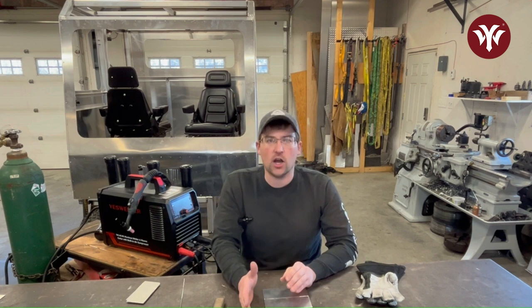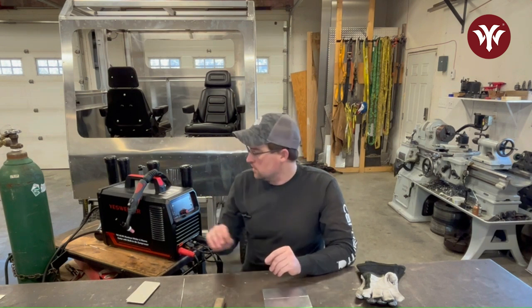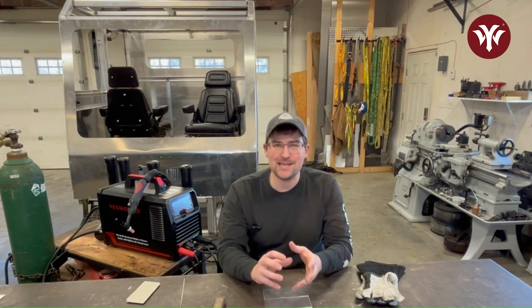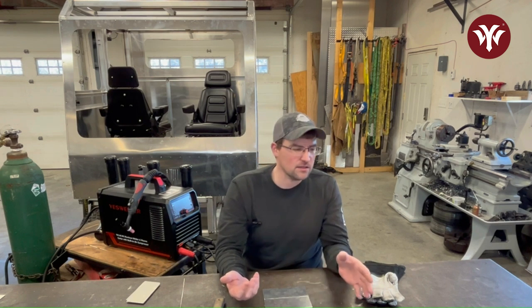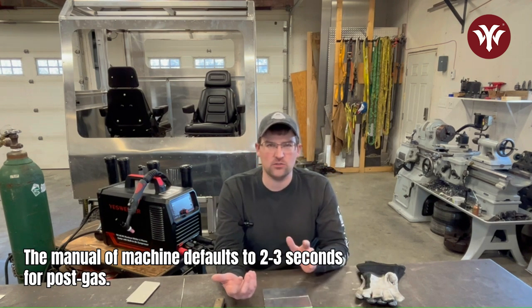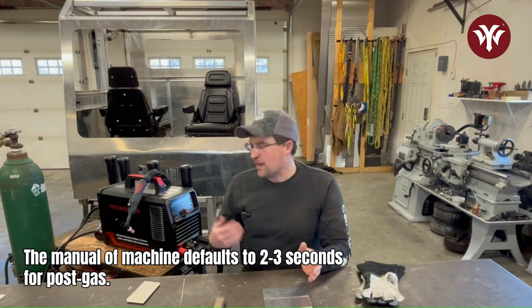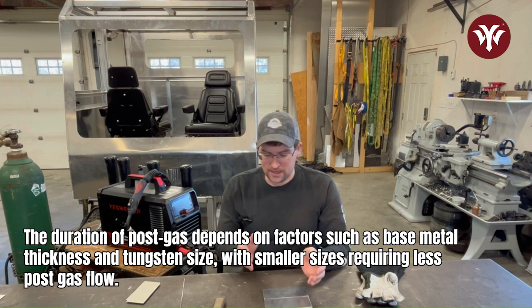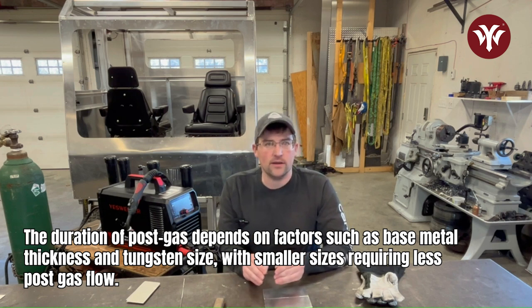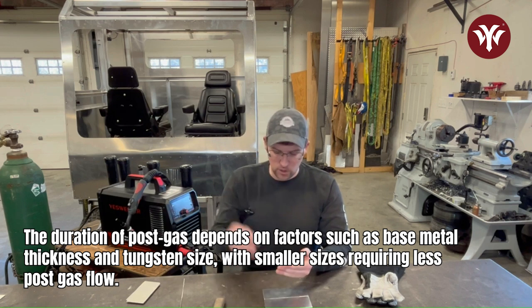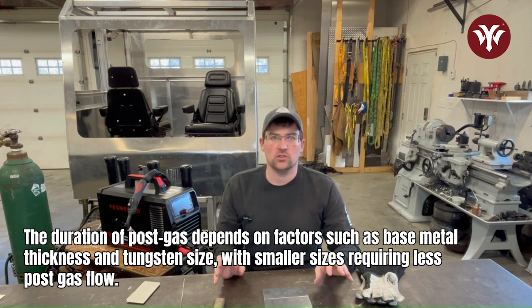If your gas shuts off right when you stop your current flow, you're going to still have molten aluminum that then becomes exposed to atmosphere and contaminates. Your tungsten is going to be glowing red hot and immediately get exposed to atmosphere, which is going to contaminate it. So post-gas, I think I was reading in the manual on this machine, defaults to 2-3 seconds. That's really going to be dependent on your base metal and your tungsten size. A smaller tungsten and smaller base material is going to cool down quicker, which needs less post-gas flow to let everything cool down to the point that it won't get contaminated when the gas is removed.